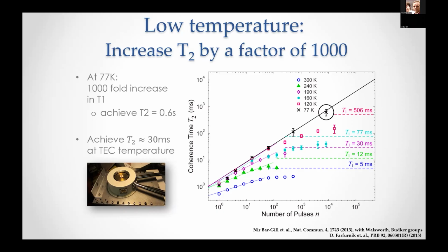There are technical issues. The technical issues are, first of all, if you think about this type of pi pulse idea from Hahn and how it cancels out from both sides, the underlying assumption, the picture that you might have in your head, is that we can do a super fast pi pulse, a delta function in time. That's of course not true. So the speed at which we can apply this rotation limits us in terms of the number of pulses that we can apply, because at some point you'll want to have many, many pulses, but there will not be any time in between.